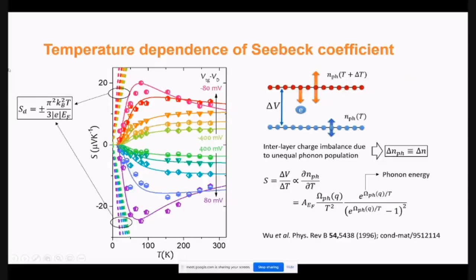But what is interesting is the thermal Seebeck coefficient: dividing the thermal voltage by delta T, I get the Seebeck coefficient. You see, the Seebeck coefficient at different gate voltages is not linearly dependent on temperature as you would expect from the Mott relation, where the Seebeck coefficient is proportional to temperature. For a given density, the Seebeck coefficient essentially increases fast and then saturates. It turns out that we can understand it in a very elegant manner, simply by looking at the phonon number in the two layers.